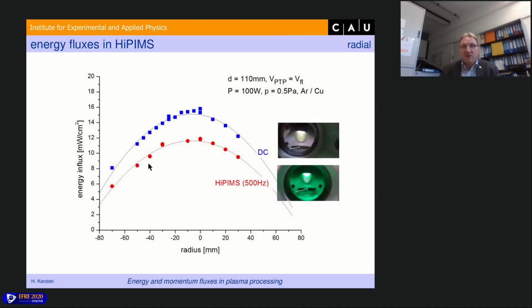So we have here a radial distribution of the energy flux at substrate position for the HiPIMS case and for the DC case. You may be astonished that the energy influx in the DC case is higher, but that is not a surprise, because here we have a continuous plasma, a continuous sputtering in the DC case, and here we have pulsed sputtering in the HiPIMS case, and the plasma is there only for a short time. We measure an average energy influx, an average power deposition, and it is even lower in the HiPIMS case than in the DC case. This is also interesting for deposition of thin films on polymer materials or thermally sensitive materials.